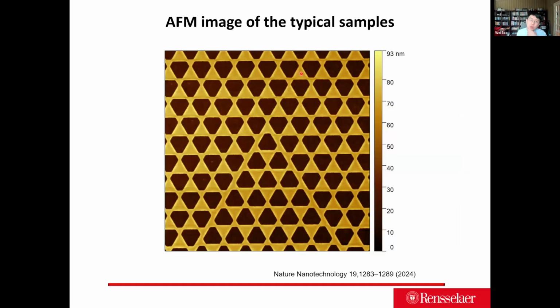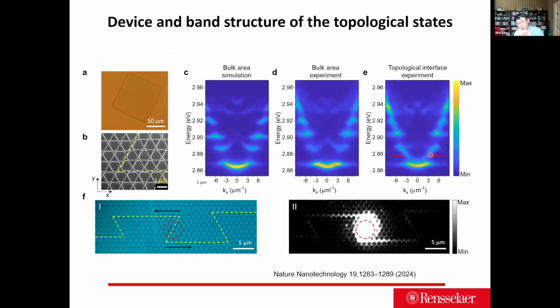I want to emphasize this. If you do AFM imaging of a typical sample, you can see our sample with the patterned 70 nanometer PMMA on top. We do show a little bit of variance. The peak-to-peak variance, for example in this region, is up to 10 nanometers, which is really big. That makes the topological edge mode's Q factor a little bit low. On the other hand, it's because we work in the energy regime of 400 nanometers, which is really close to the blue light, UV regime.